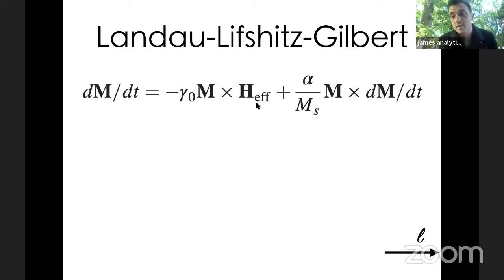H effective is the effective field in some sense applied by the spin polarized current. And the basic idea is that this effective field term is helping you rotate your spin in two ways. One, by a typical M cross H term, which is the way we think of a real external magnetic field affecting our spins.